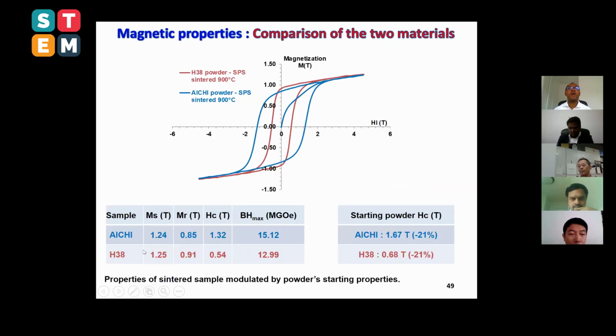And then how about now the samples we performed by SPS? By SPS, this is the result you obtain. Again, you have the hysteresis curve, the magnetization dependent on the magnetic field, for both powders, Aichi powder and recycling powder, the red color here. The results are quite close, but the main parameter is the energy, where you deduce the magnetic energy in both curves: roughly 15 megagauss-oersted in the commercial powder and roughly 13 in the recycling powder. But the coercive magnetic field was less, by 21%, compared to the starting powder, like you can clearly observe here.